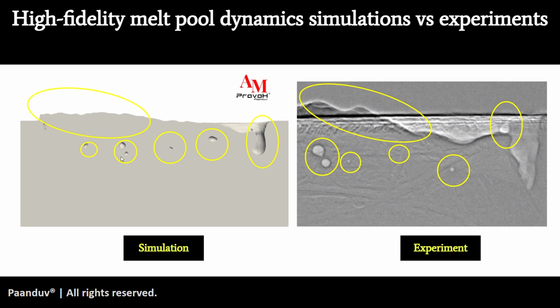Similarly, the pores are almost spherical in nature, as we can see in the experiment and in the simulation. The pores are not only spherical, they are almost at the same location. So if you observe this particular circle, and if you observe this particular circle, they are quite identical. Then you have another pore here, you have another pore here, this pore is probably this one, and then even a pore is formed here, where you can see a slight hole. You can see a slight hole right here.